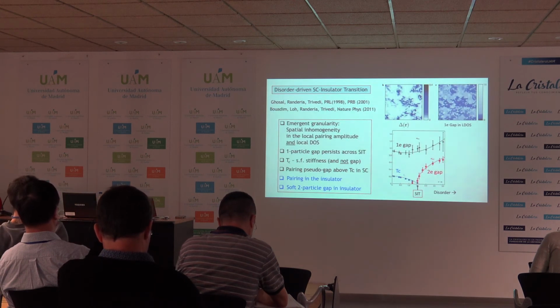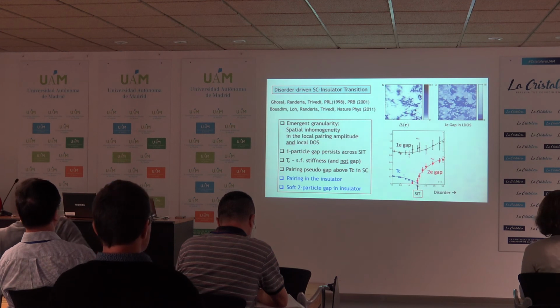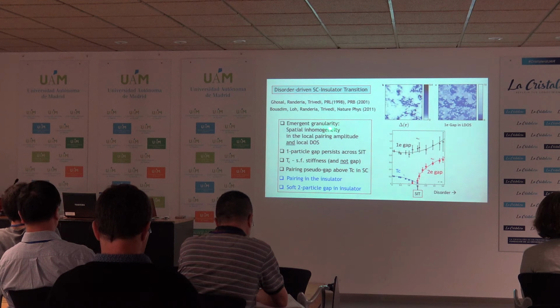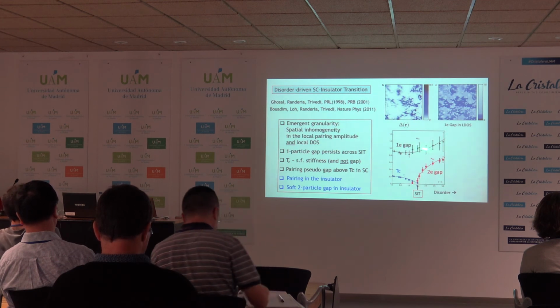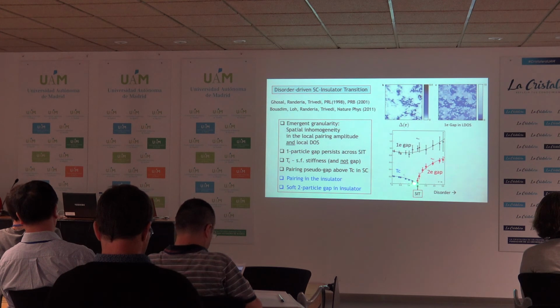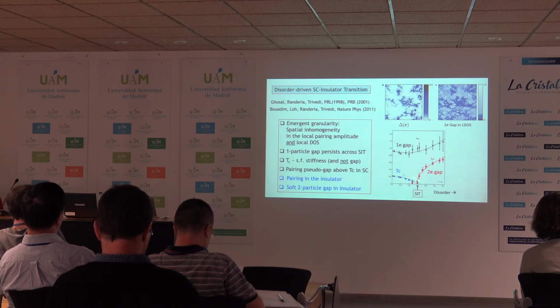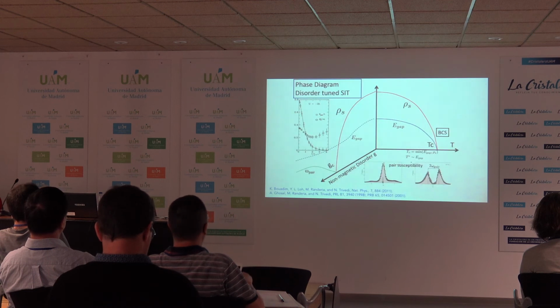Okay, so ending the second part, the key points are listed here. There is emergent granularity, spatial inhomogeneity in the local pairing amplitude, and as I said, the one-particle gap persists, the two-particle gap is going soft at the transition, and the stiffness is controlling the behavior on the superconducting side.